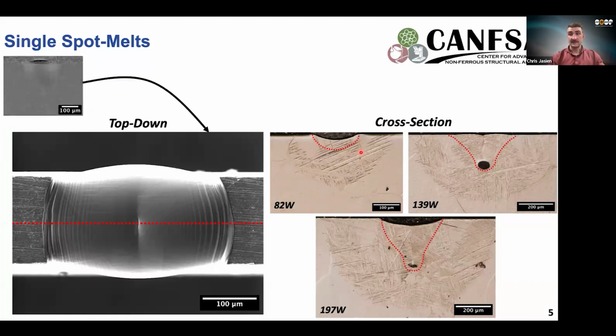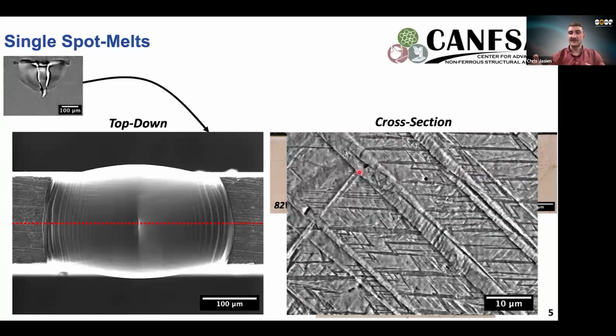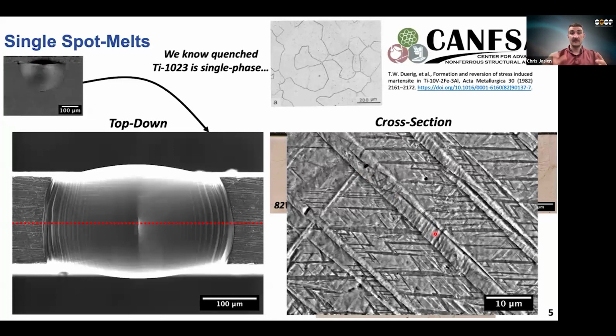And so we actually see some distinguishing features that wouldn't necessarily suggest what we would think. We're seeing maybe some different phases, maybe something that's a little bit more needle-like. And when we zoom in on that, we can see it's a very complicated structure. It's not what we would expect to see from these alloys, which, if you remember, were supposed to be in one single metastable phase after they were rapidly cooled. And so the literature has shown that this material, when it's rapidly cooled, is single phase and behaves like we think. So it causes us to scratch our heads and go, okay, what is actually going on here?